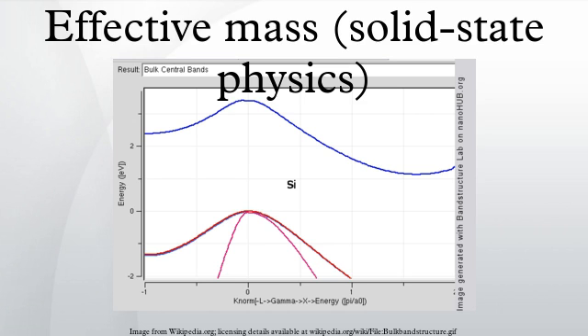Still, in crystals such as silicon the overall properties such as conductivity appear to be isotropic. This is because there are multiple valleys, each with effective masses rearranged along different axes. The valleys collectively act together to give an isotropic conductivity. It is possible to average the different axes' effective masses together in some way, to regain the free electron picture. However, the averaging method turns out to depend on the purpose.